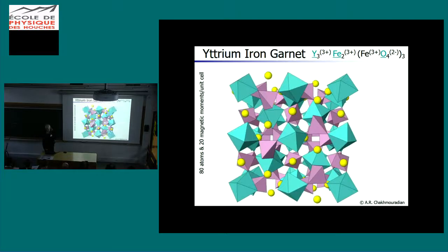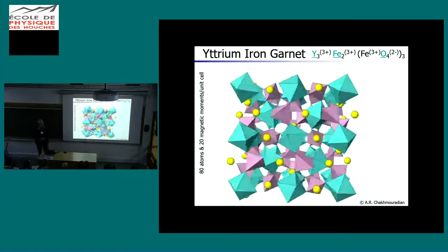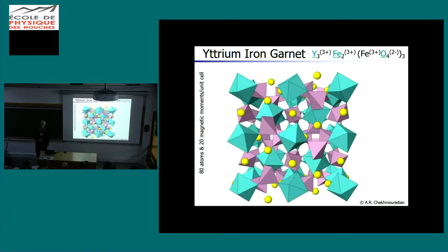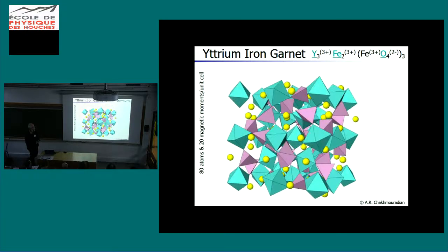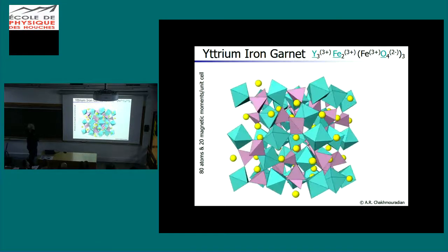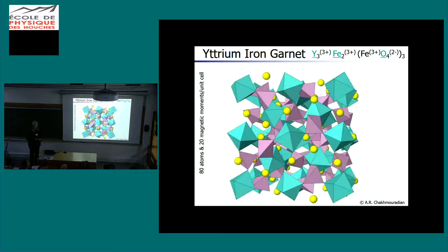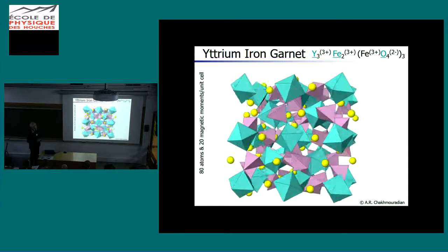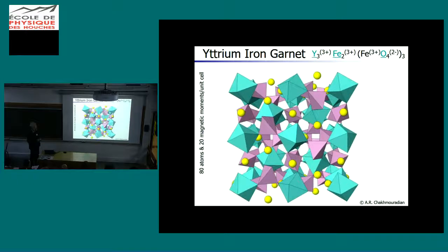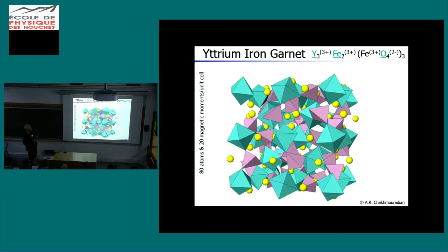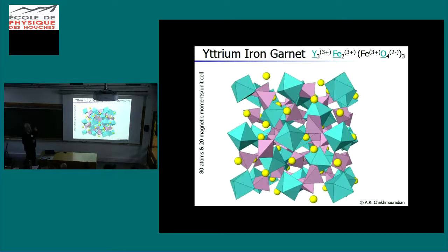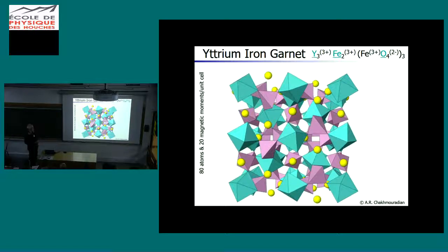Many people will talk about YIG later, but I'm the first one, so let me introduce this material. It's a real monster with 80 atoms in the unit cell. It consists of a scaffolding of oxygen anions, which leave a lot of space for the yttrium cations, whereas the iron cations are in these octahedra and tetrahedra, which you see here.